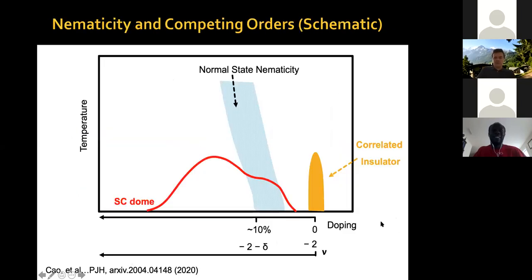So the picture that is emerging from these first two parts of the talk is the following. We have a phase diagram, temperature versus doping. I'm showing here the correlated insulator state at 2 holes per moiré unit cell, and then we add extra holes. Our superconducting dome seems to have a depletion, which coincides with the region where in the normal state you have anisotropies. You have normal state anisotropy, and that causes a depletion of your superconducting Tc. Now, in addition, everywhere in the superconducting dome, we have nematicity. We have an anisotropic response of the superconductivity.